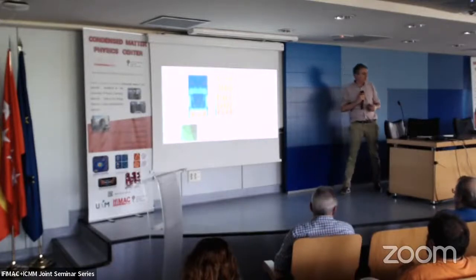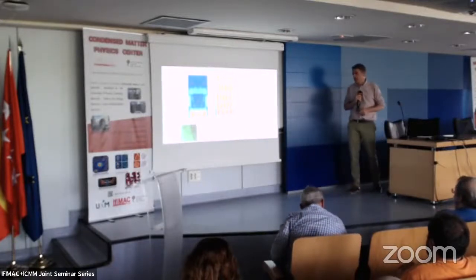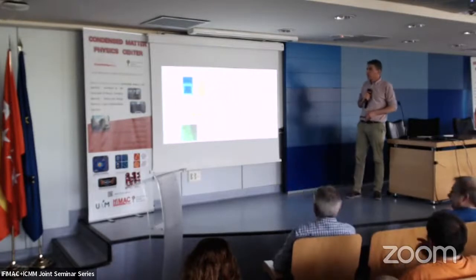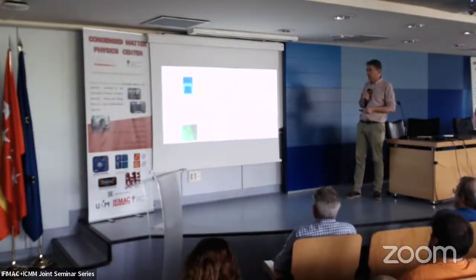So this is fundamentally different from what was done in the case of copper. We can follow all the physics, like making use of the Fabry-Perot expression. We can make all these nice fits. We can also calculate the reflection coefficient as a function of the bias voltage, and this is what happens in copper. You see that it's a very flat dependence.